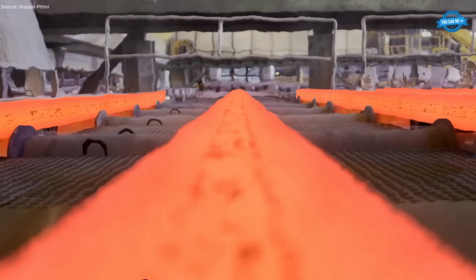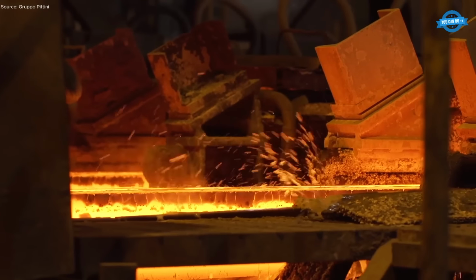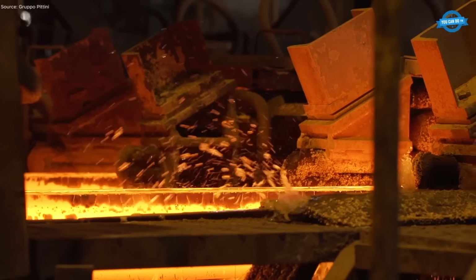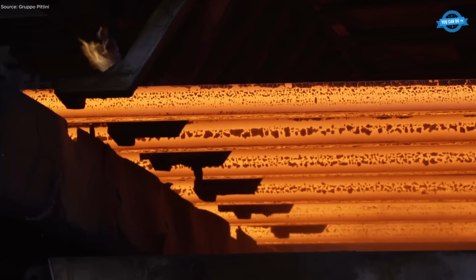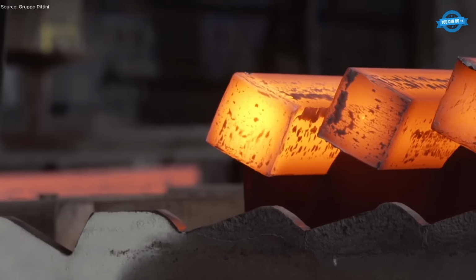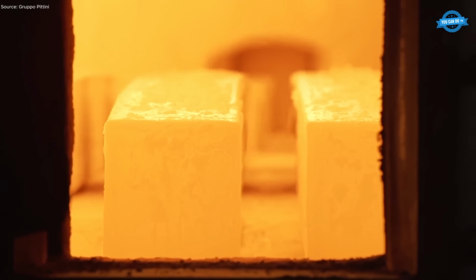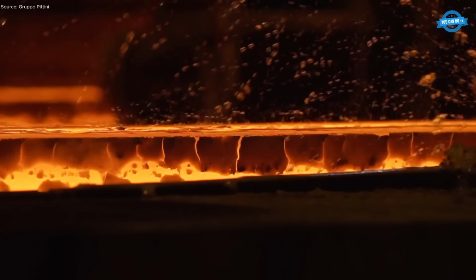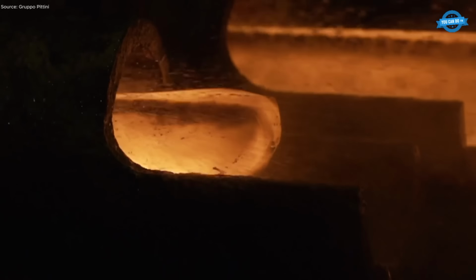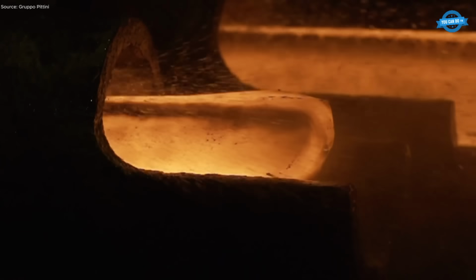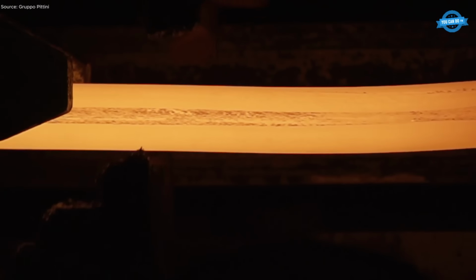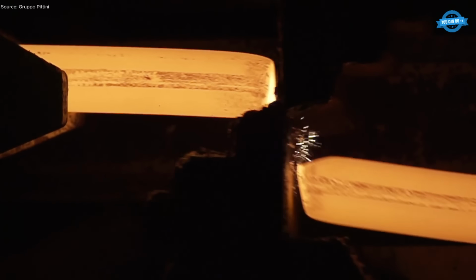Once the final diameter is achieved, the wire passes on to controlled cooling conveyors, where the cooling rate is adjusted to create the desired microstructure and mechanical performance. The resulting wire rod is then formed into coils, each weighing around 2 tons, secured by automated bundling systems. The dimensional range covers smooth rods from 5.5 to 20 millimeters and ribbed rods from 6 to 16 millimeters.